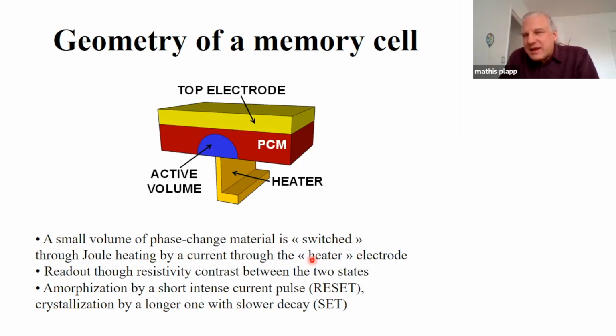Once it's heated up, they cut the current, and then the heat dissipates away in the material. That controls the velocity of the quench. And the information is read out by a small current, because when you apply a voltage, the two states, the amorphous and the crystalline state, have very different conductivities. So you apply a tension and you read out the current that goes through. In this way, you can read whether the bit is 1 or 0.